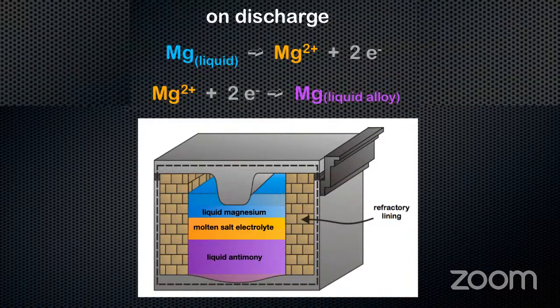So what happens? On discharge, the magnesium wants to alloy with the antimony. But these three, I forgot to tell you: the magnesium is insoluble in the salt, and the salt is insoluble in the antimony. Liquid metals and molten salts are, to a first approximation, insoluble. So they stratify like salad oil and vinegar. Separated.